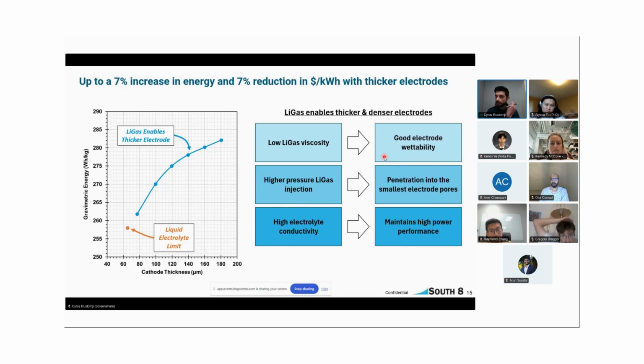On top of that, we're injecting these solutions under pressure into the cell, which allows us to penetrate those very thick electrodes into every small little nanopore within that electrode. And lastly, we still maintain a very good electrolyte conductivity, so we can maintain that high power performance that everyone knows and loves.